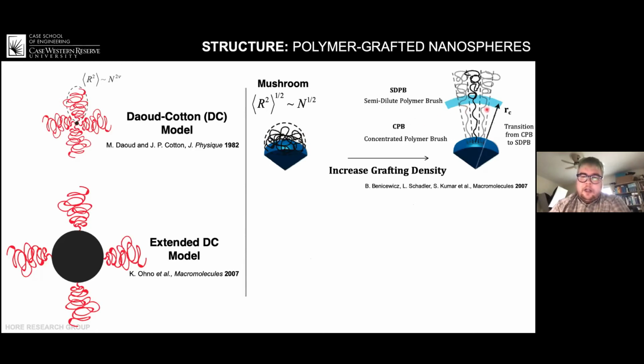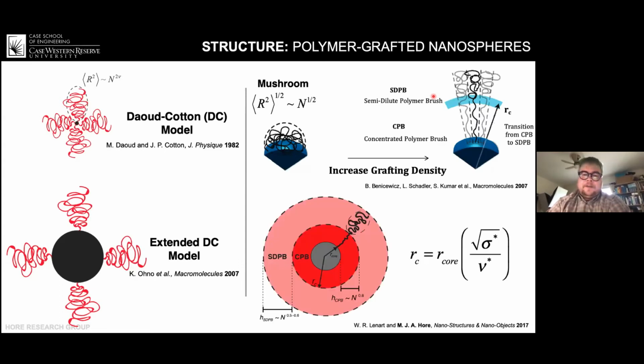You have a concentrated polymer brush close to the core, and after a cutoff distance R_C here, it transitions to a semi-dilute polymer brush. So what I want to emphasize here is that these 2 regions are differences in concentration, but there are not necessarily differences in conformation. But the cutoff distance between these two regions, using the Daoud-Cotton model, can be expressed as the product of the radius of the nanoparticle, the square root of a reduced grafting density of polymers, and this term in the denominator, the excluded volume, that I'm going to talk about in the last part of the talk today.